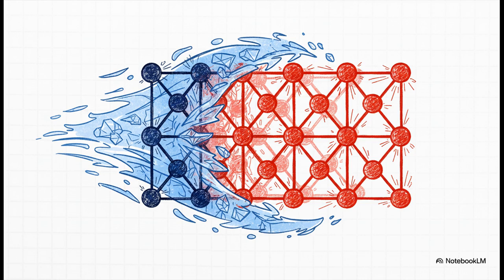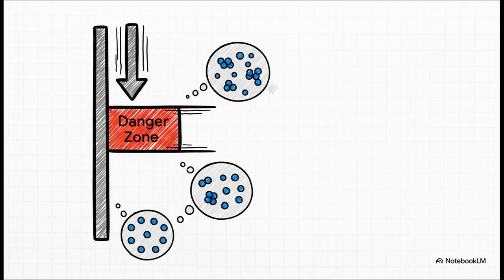And to do that, we have to cool the metal from over 500 degrees Celsius down to near room temperature with extreme, incredible speed. We're basically freezing those dissolved atoms in place before they have a single chance to move. You see, every alloy has this danger zone, a temperature range where those dissolved elements are just desperate to clump together into weak, useless little groups.